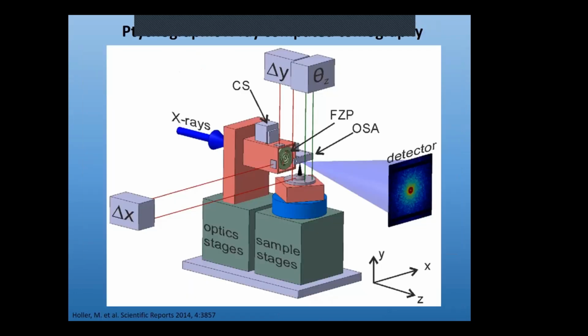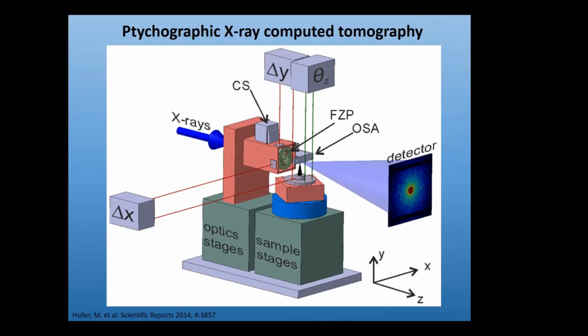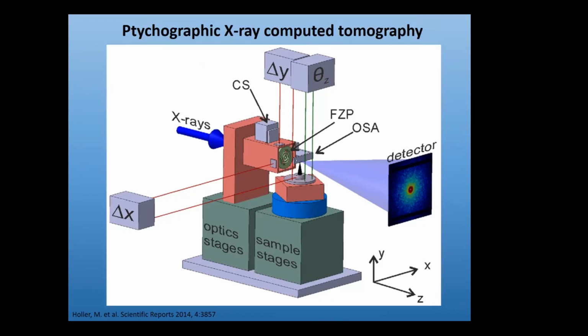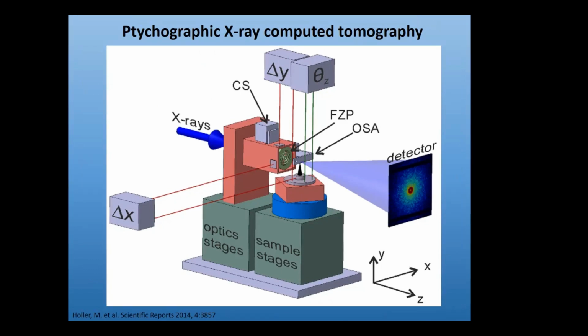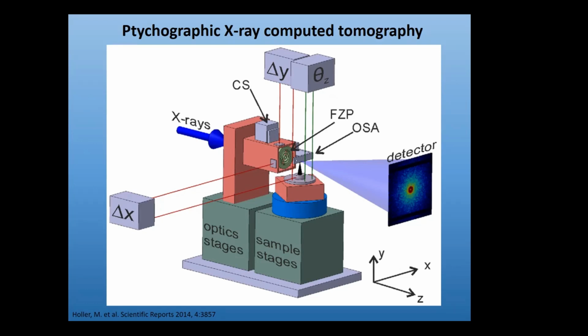And to finish the part on the coccolith, I'm going to talk about the work of my current PhD student, Alex Trikas, using ptychographic X-ray computed tomography. This is a synchrotron-based technique that we can use to image sample objects in 3D using X-rays, but it's different from tomography. The way that it works is that you fire the X-ray at a sample, and what you collect is a coherent diffraction pattern. And we just raster the X-ray through the sample, collecting overlapping diffraction patterns.